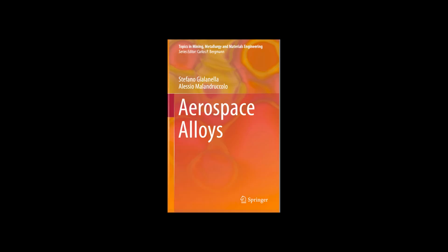Very important, especially for creep resistance. Small additions of elements like boron and zirconium segregate to the grain boundaries and strengthen them, making it harder for grains to slide past each other at high temperatures. But the really unique thing is the gamma prime phase, right? That's the star player, yes.